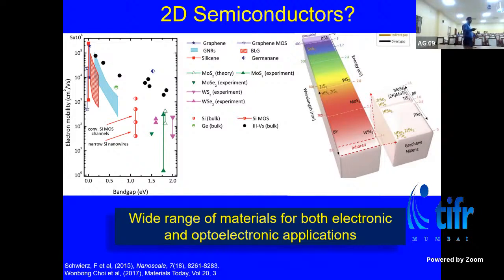For example, if you look into the carrier mobility, electron mobility is a measure of how fast the carriers would be in a system, how efficiently they will move, they'll drift in a particular system. If you look into the numbers, compared to the conventional bulk materials, the mobilities offered by the 2D systems, particularly graphene and other 2D materials, are either comparable to silicon or better than silicon. What is important to notice here is that when we say comparable to silicon, we are talking about the bulk silicon mobility. But here we have a 2D material, which means it's one atom thick. When you compare thin silicon, the quantization effects kick in, and therefore the mobility of that kind of silicon would be much smaller compared to what we get in a 2D semiconductor. So one can say that 2D materials certainly offer much better transport properties compared to silicon for comparable scenarios.